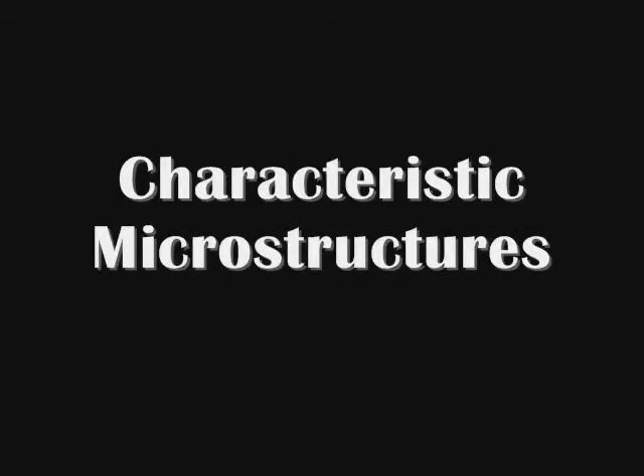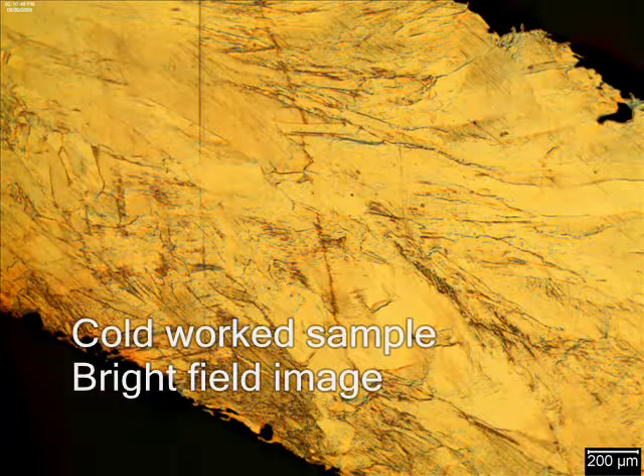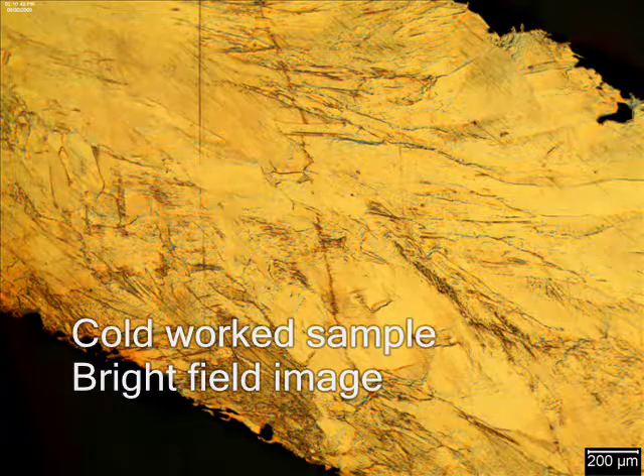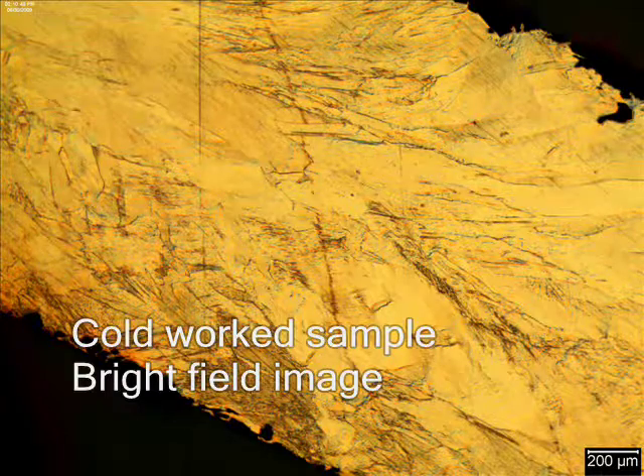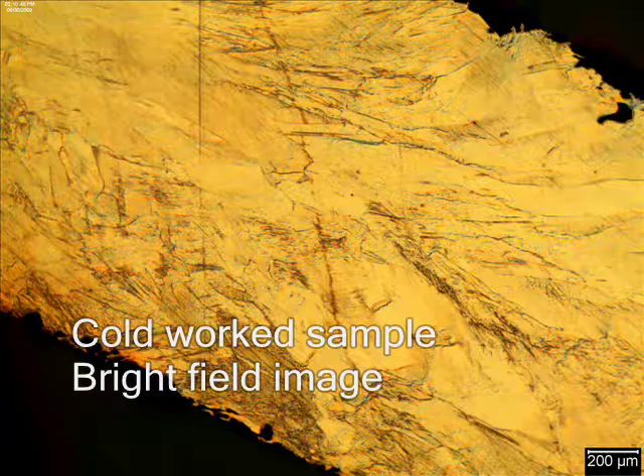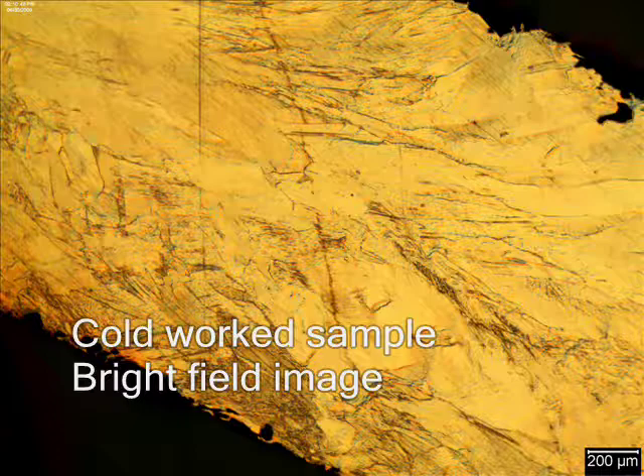There are a few characteristic microstructures, and we'll show you 3 here. In a typical cold work structure, such as this cold hammered copper, the grains are elongated in one direction. This is a bright field image, and in bright field imaging, the grains appear bright, while the grain boundaries look dark.